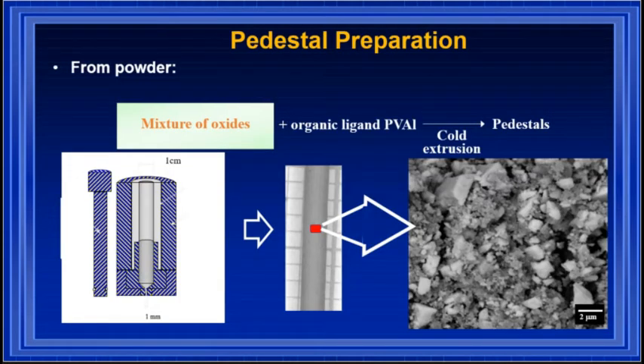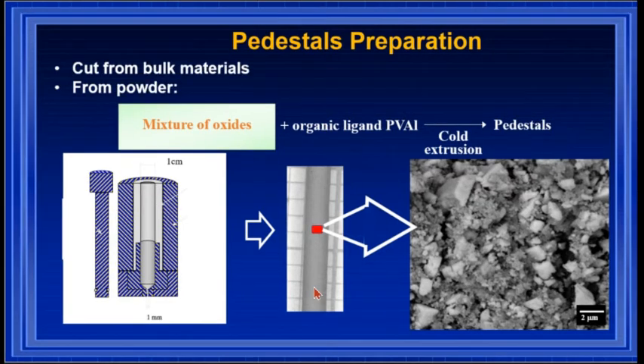The pedestal preparation, in our case, was done just with a mixture of our oxides with the introduction of an organic binder, polyvinyl alcohol, and then through a cold extrusion process we can produce cylindrical pedestals. This pedestal we use as it is, without sintering, to produce the single crystal fibers. This is the case where we produce the lanthanum aluminate fibers and zircon fibers that we are going to use in this work.